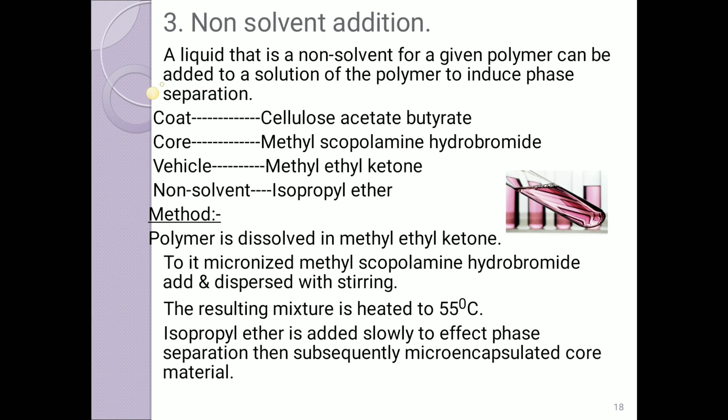Then how do we obtain the microencapsulation? The polymer is dissolved in methyl ethyl ketone. To it, micronized methyl scopolamine hydrobromide is added and dispersed with stirring.